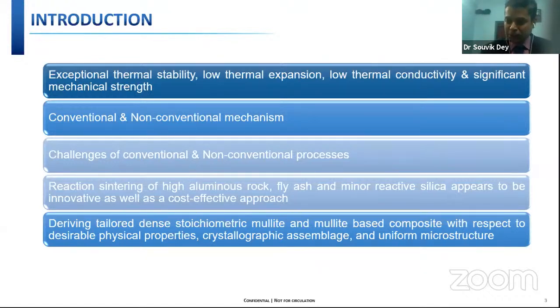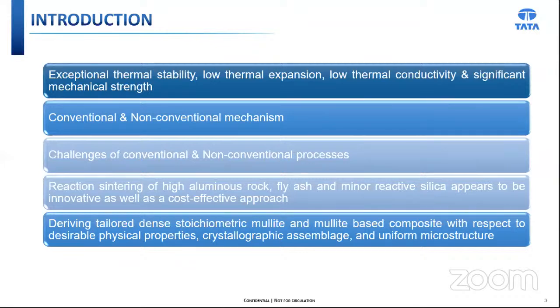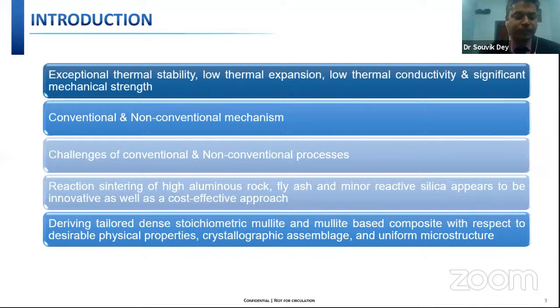Now, there are two synthesis routes. The first one is the conventional mechanism by using clay minerals, aluminosilicates, or clay alumina or clay bauxite having relatively coarse particles. And the second one is the non-conventional technique. Each mechanism has its pros and cons. In the conventional process, the processing temperature is energy intensive, but in the conventional technique, the mullite formed is not of outstanding properties as good as the mullite formed in the non-conventional technique. However, mullite derived from high purity precursors, that is in the non-conventional route, is quite expensive and not a viable option for its large scale production due to low yield and complex processing techniques.